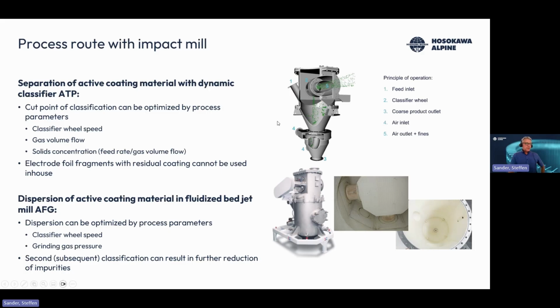And you need to separate these two fractions, and we use classifiers for this, mostly this deflector wheel classifier. So here you have a deflector wheel rotating with high speed, and you suck in an airstream or gas stream, you can suck the material through. And this air volume flow is set into rotation by the classifier wheel. And so you have two different forces acting on the particles.